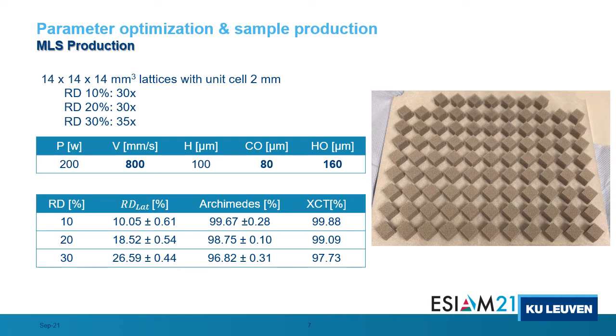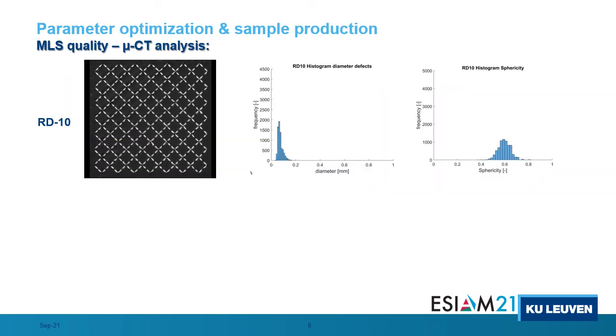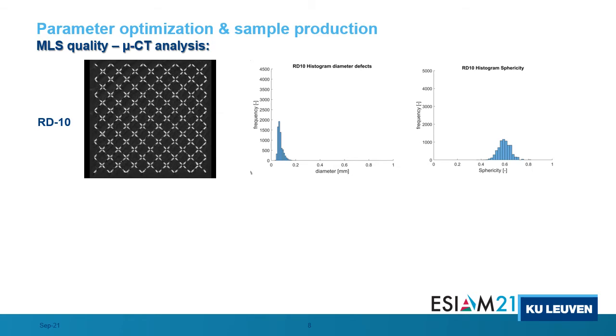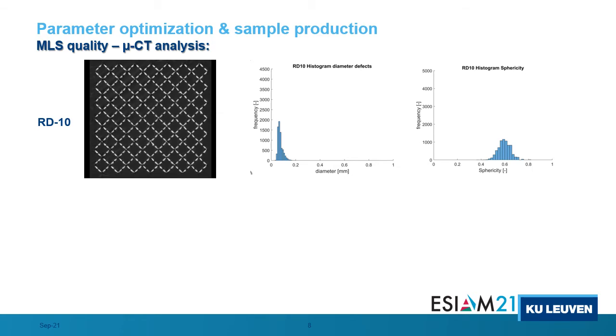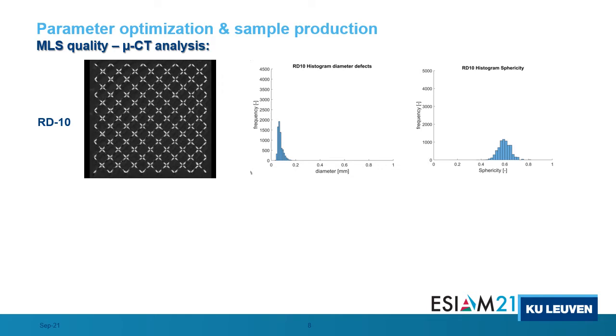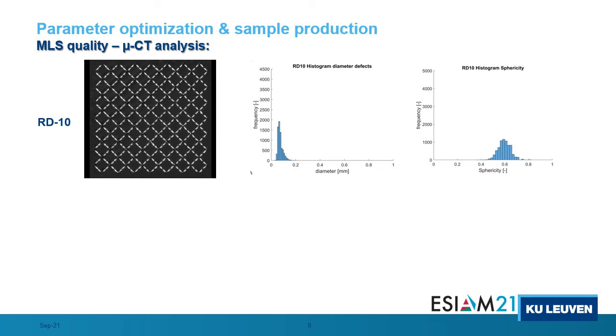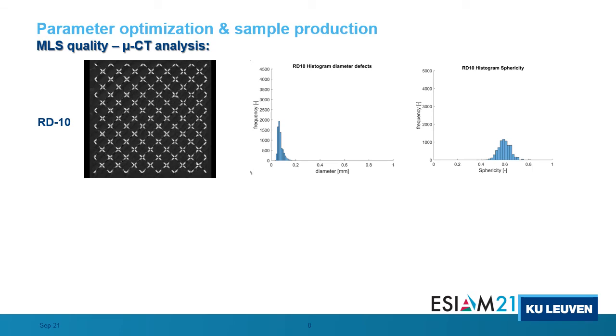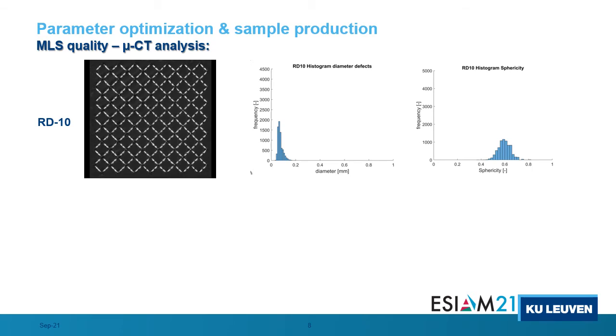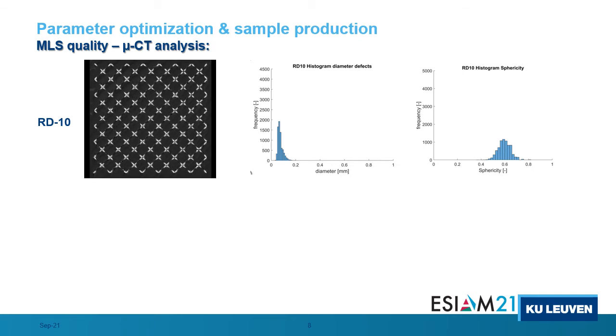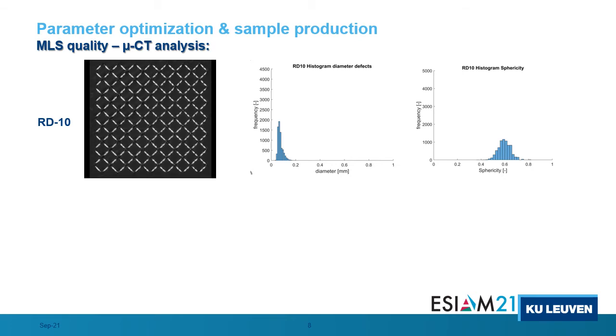The internal porosity of these structures is also investigated using both Archimedes and micro-CT analysis. And it can be noticed that for increasing design relative density, more and more defects are present in our structures. The CT scans allowed us to take a closer look at the defect populations generated during the manufacturing process. For RD10 coupons, it is possible to distinguish well-defined struts with a very limited amount of internal residual porosity. These internal defects are very small and spherical, indicating that these pores consist of entrapped gas in the material.